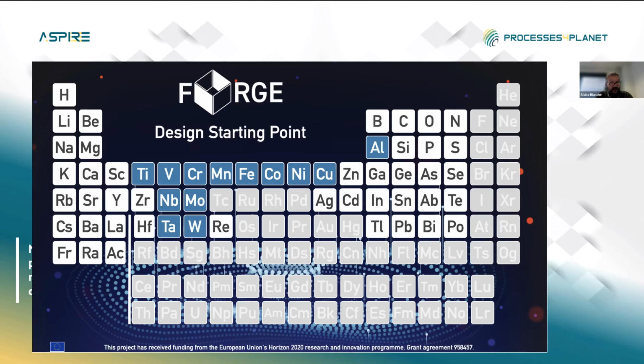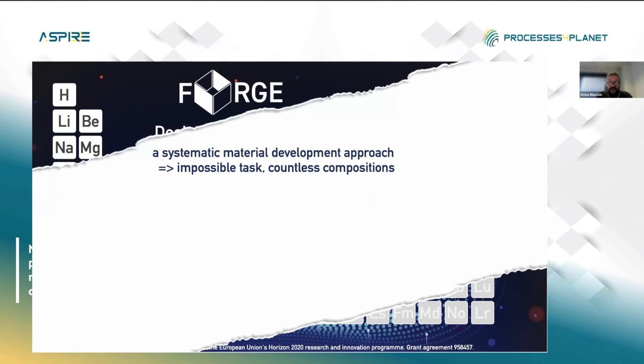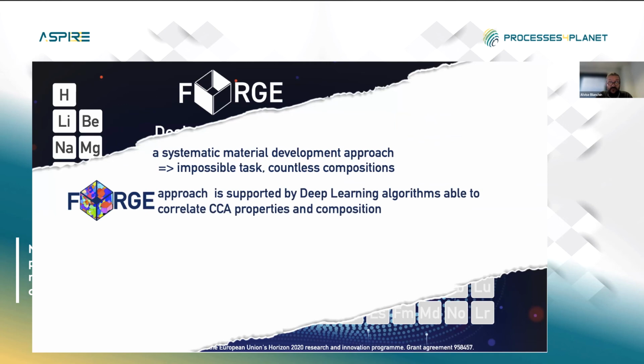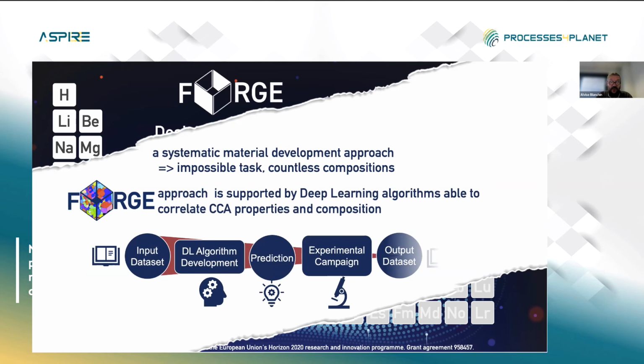But even with this small group of materials, it's difficult to have a complete and systematic development approach. It can be an impossible task given the countless compositions, as we have seen also in other presentations. So the Forge approach is to be supported by a deep learning algorithm, able to correlate the properties of the compositionally complex alloys and the composition. This can be done starting with an input data set, developing the algorithm that gives a prediction, and this prediction has to be validated against an experimental campaign that will eventually provide an output data set. This needs to be reiterated to further refine the algorithm output.